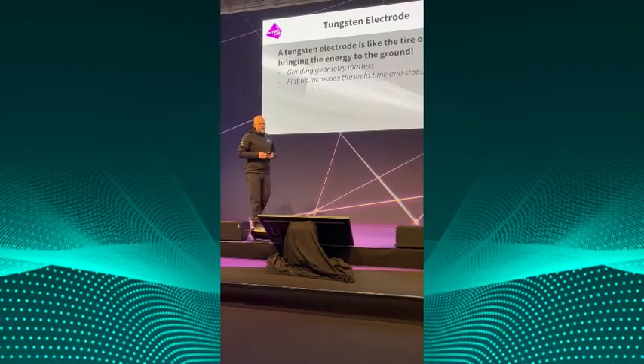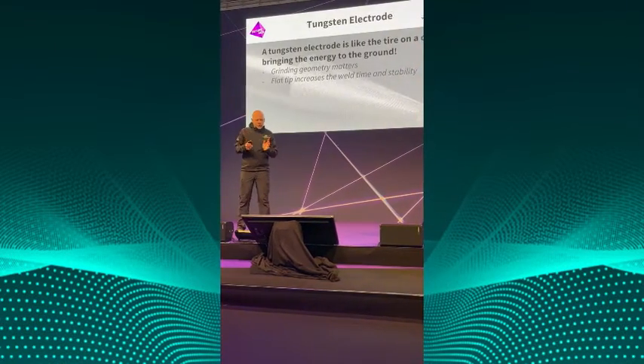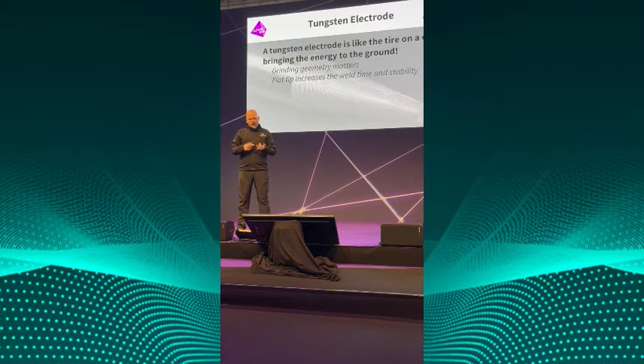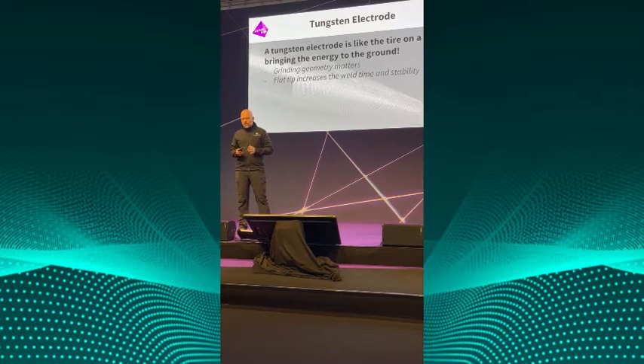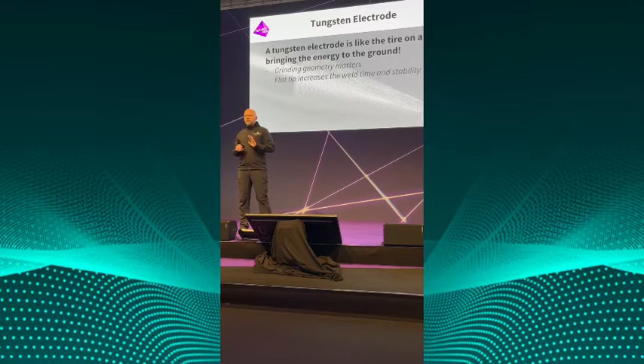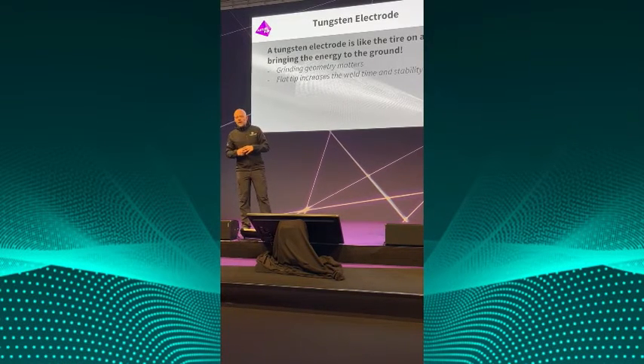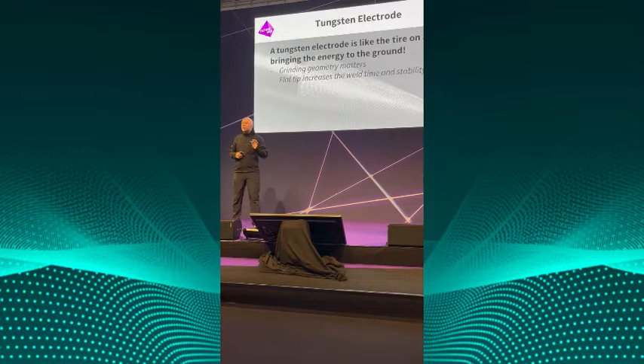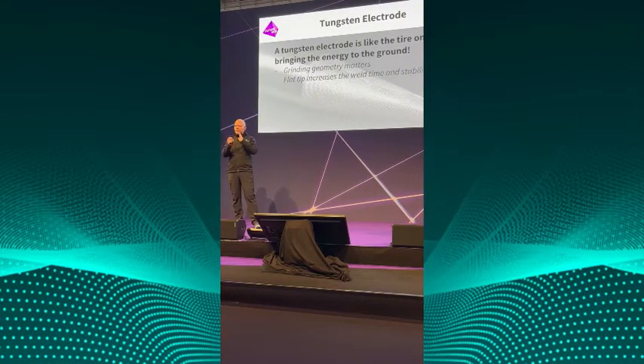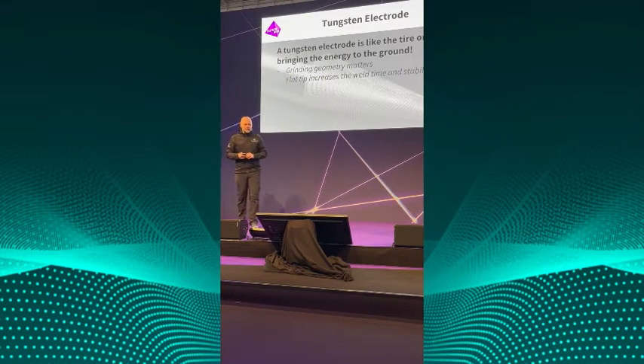A flat tip on the tungsten electrode increases welding time because you don't overheat the very tip of the electrode, and the overall process stability, like penetration, sidewall fusion, is far more stable. And against every myth or half-truth, it will not decrease arc stability or whatnot.